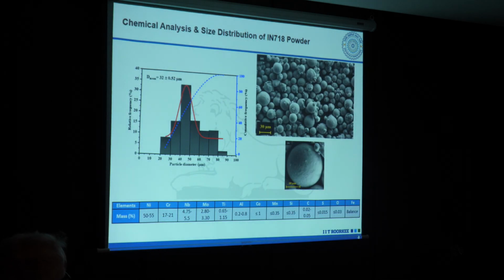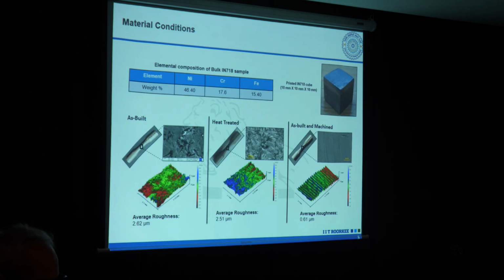This is the chemical analysis and size distribution of the powder, so I'll skip this one. The mean diameter of this powder is 32 micron, and this is the chemical composition. Then we selected three different material conditions. One is as fabricated, the second is heat treated, that is the stress relieving heat treatment, and the third is where we fabricated the sample and then machined it.